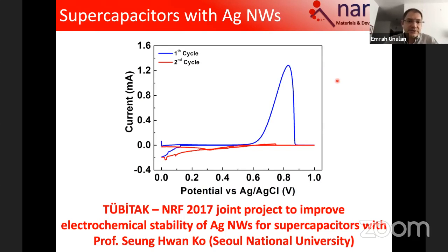Let me talk about another instability. This is electrochemical instability. If you are going to make any electrode, for instance for energy storage or another optoelectronic device like electrochromic displays, you need to apply a potential in a solution or in an electrolyte, if you wish. If you do this on top of silver nanowires, as you see in the first cycle, there is an oxidation, which is irreversible. If you go to the second cycle, you cannot really read current because you completely oxidized the silver nanowires irreversibly, and your network is lost. So we need to also take care of this electrochemical instability issue in addition to the environmental instability issue.